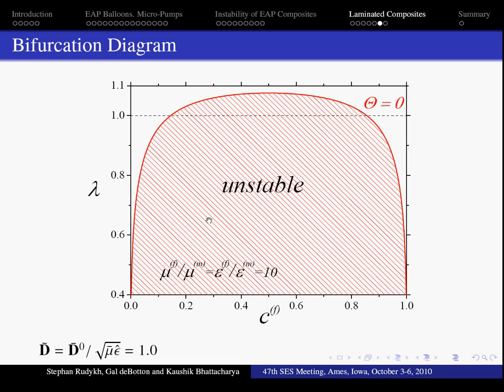The present example is obtained for composite with phase material contrast of 10 and the normalized electric excitation equal to 0.2. The unstable domain is symmetric with respect to inclusion volume fraction 0.5.